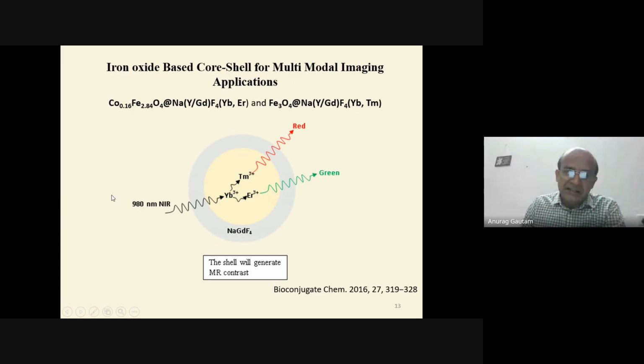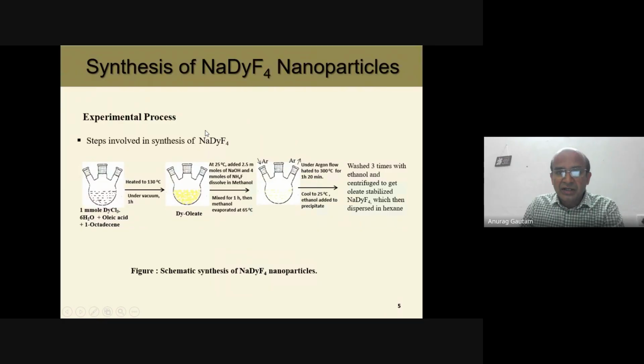This is done in the setup, like if we have to give an IR light, 980 nanometer laser light, a diode laser, or whatever laser source there is at that wavelength. That will excite the Yb, and the Yb will transfer energy to Tm, which is a red emitter, and this will also give the green emission from erbium-3. So for this particle, we can also use it for MR contrast. Here we can generate MR contrast for this core-shell structure. So how do we work with the lanthanide to produce the contrast?